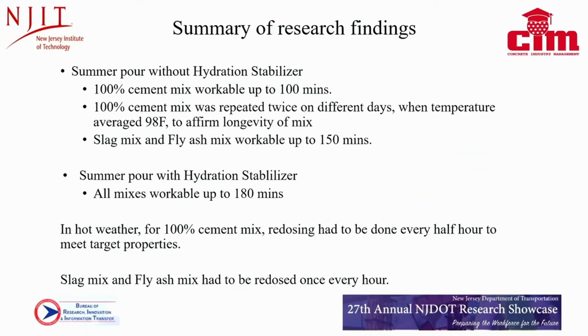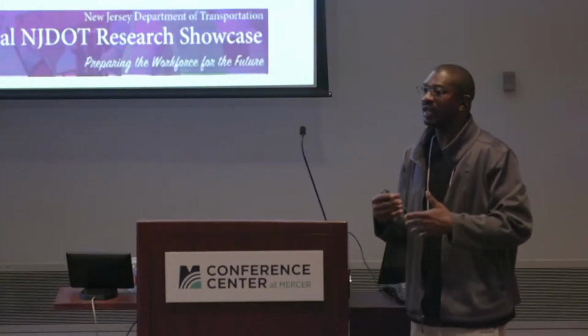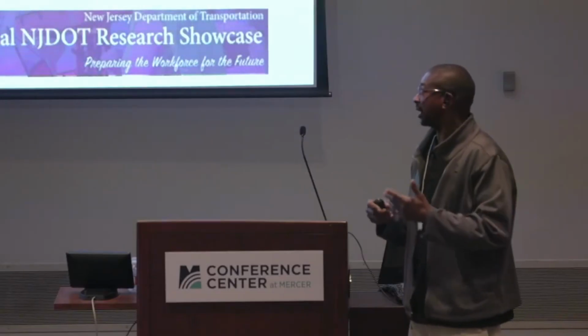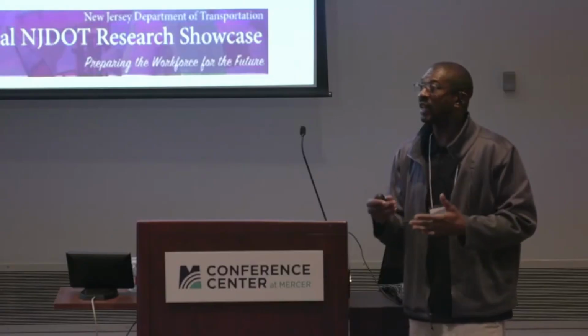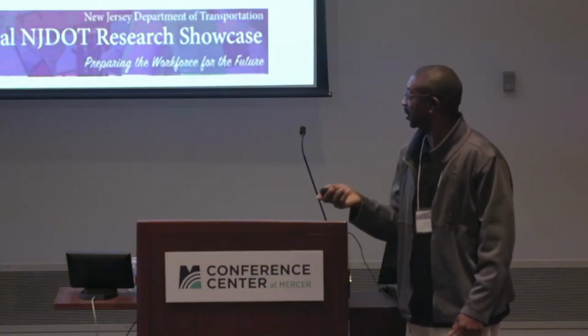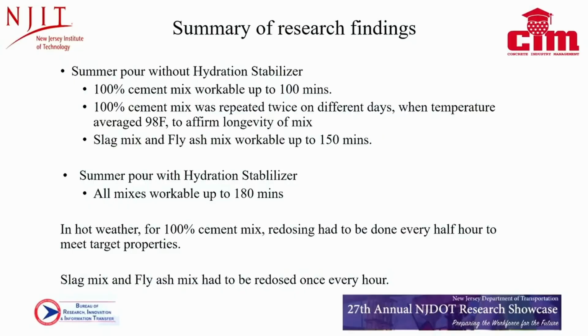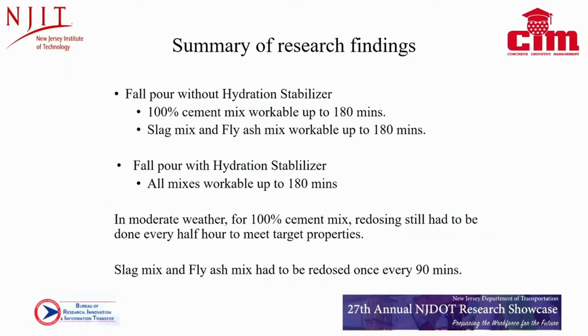All right, so summary of the research is that we found that the mixes were workable up to about 150, 180 minutes. The 100% cement up to about 100 minutes, which was just a little bit over the 90 minutes. I think I mentioned earlier that in the hot weather for the 100% cement mix, we had to redose with high-range water reducer and air entrainment just about every 30 minutes, whereas with the slag and the fly ash, just about once every hour. So the slag and fly ash was able to maintain its slump and workability much longer. Here we go, slag and fly ash, work up to 180 minutes.